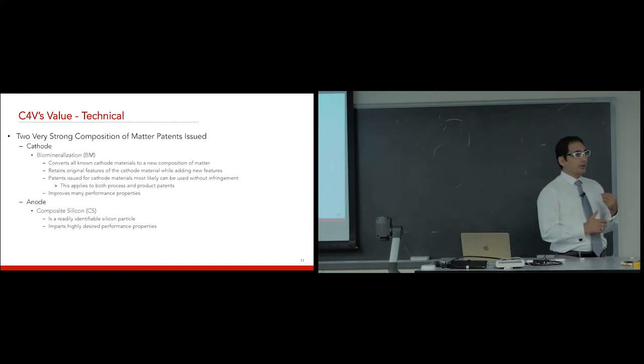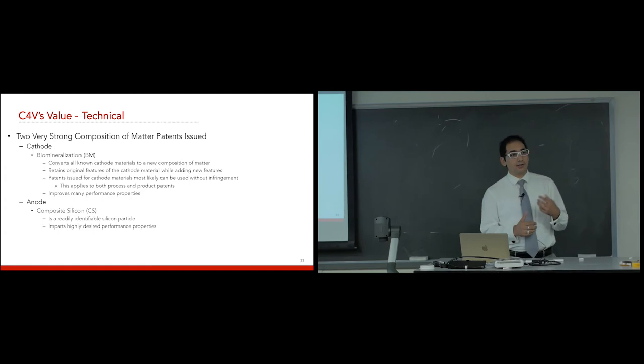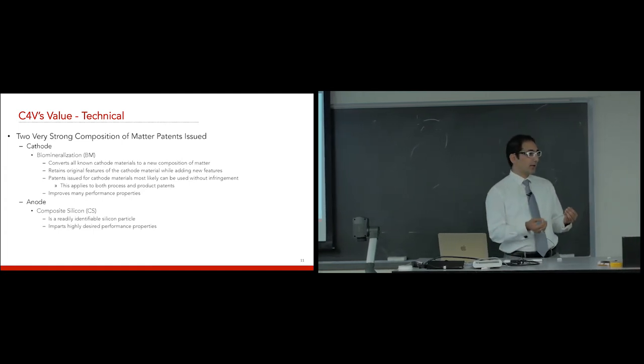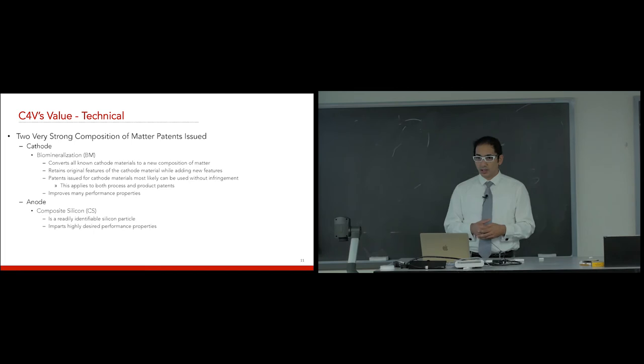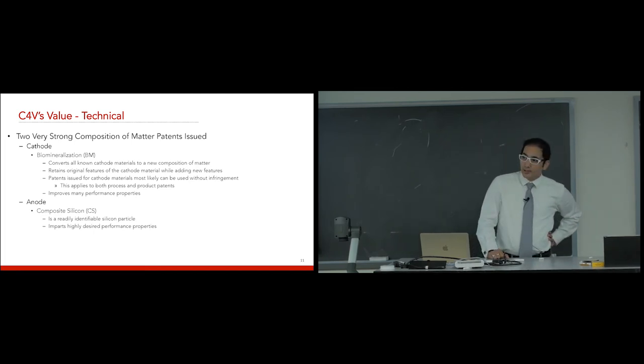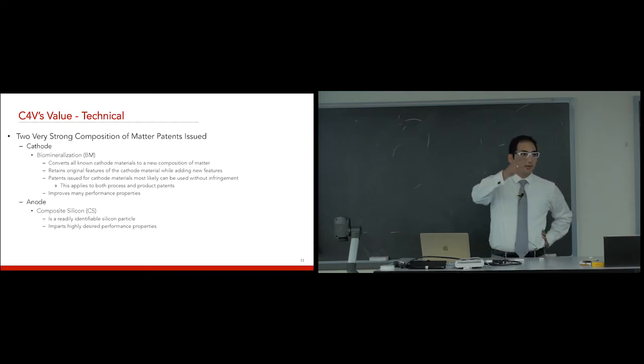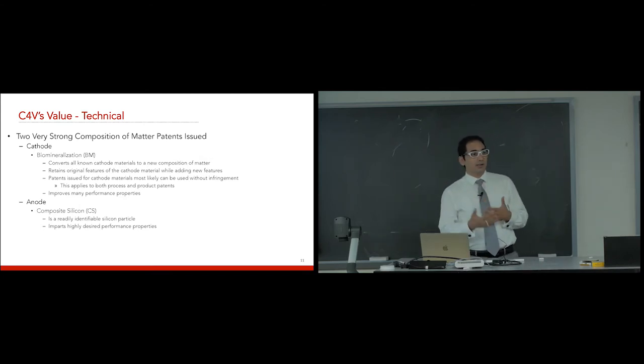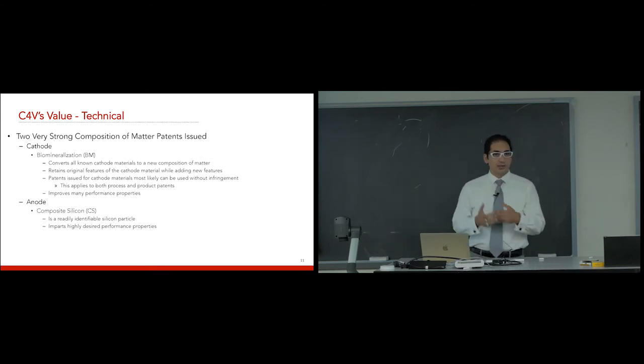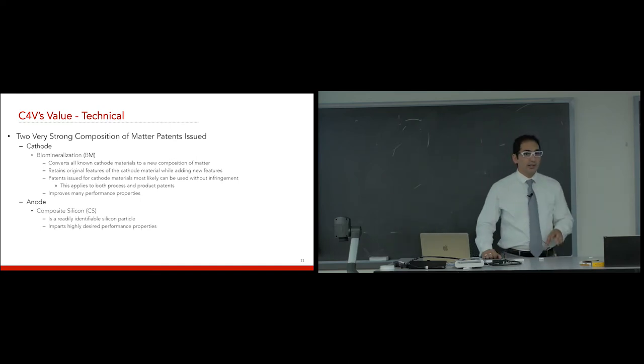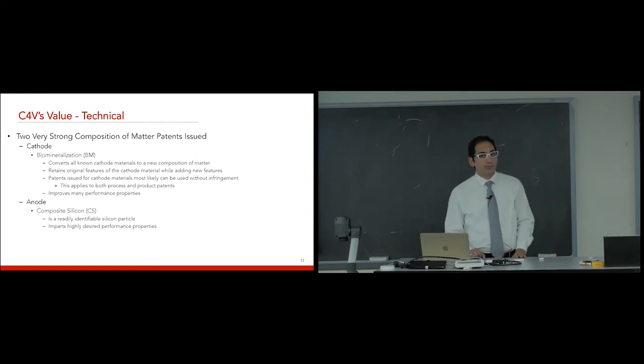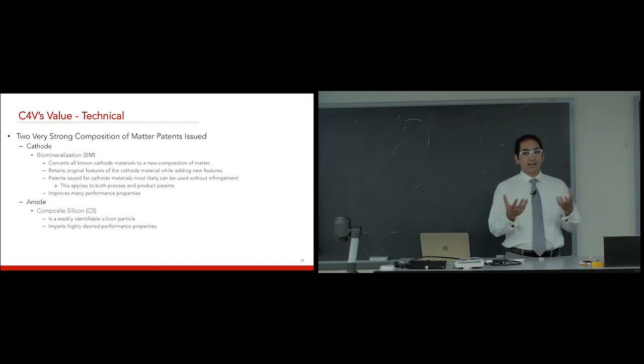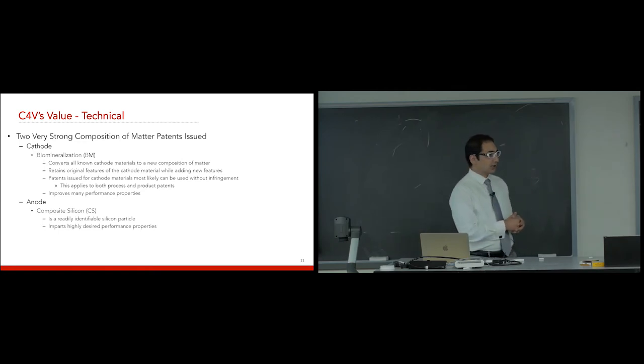You have the solvent, or in fact the salt in the electrolyte, that's fluorine based. The moment it reacts with water or moisture, it forms hydrofluoric acid. And as you all know, hydrofluoric acid is one of the most toxic acids known. So it starts corroding and killing components of the battery. As you cycle, charge and discharge your battery, and as side reactions happen, it starts forming the acid, and your battery eventually dies. So if there is a way or mechanism to capture that fluorine or avoid the hydrofluoric acid formation, that's just one example. This is how the whole biomineralization technology